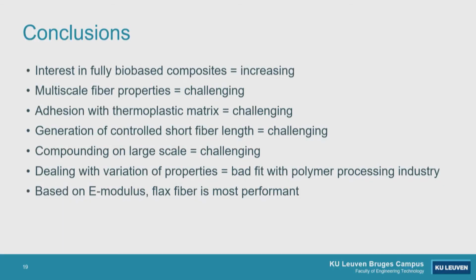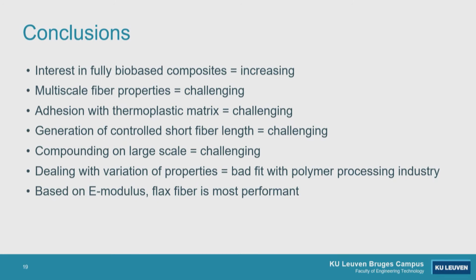So, some conclusions. For sure, there is lots of interest in these fully bio-based composites, and in trying to understand what's going on and trying to predict it, not just doing trial and error on equipment, but trying to understand what's happening inside with numerical simulation tools. That's challenging for us. Multi-scale fiber properties are also challenging, because, as I indicated briefly, it's not only pure fibers which are added inside. Sometimes you have a composite inside a composite, and trying to model this in a mechanical way is challenging. It's not written on the fibers what the amount of fillers is, what the amount of fibers is, and what's really in there. Adhesion with thermoplastic matrix is also challenging.